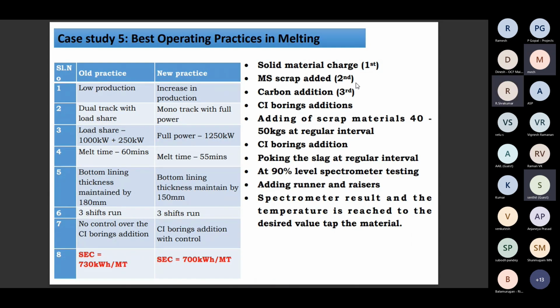Best operating practices in melting, same thing. This one is dual track furnaces with load share, mono track with full power, and the load sharing is happening. Earlier it was 1000 kilowatt plus 250 kilowatt. Now it is given as full power, 1250 kilowatt. The main thing here is that the solid material is charged first, then the MS scrap is added, and the carbon addition is third. Then CI borings addition, adding the scrap materials 40 to 50 kgs at regular intervals, and CI borings addition. And the main thing is poking the slag at regular intervals, so the slag is removed periodically.